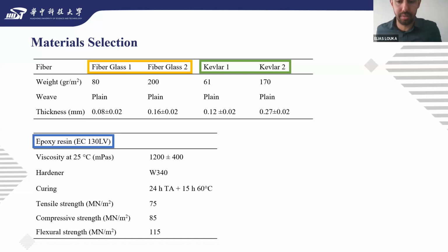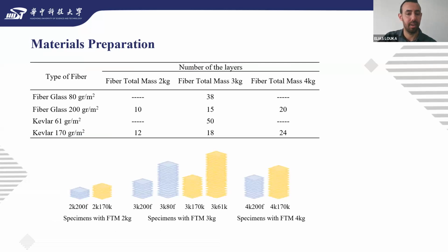About the material preparation, to examine the volume fraction of the specimen created by different number of layers for fiber total mass of the non-impregnated fiber, we use 2 types of Kevlar and 2 types of fiberglass. The mass per unit area for fiberglass is 80 and 200 grams per meter square, and for Kevlar is 61 and 170 grams per meter square.